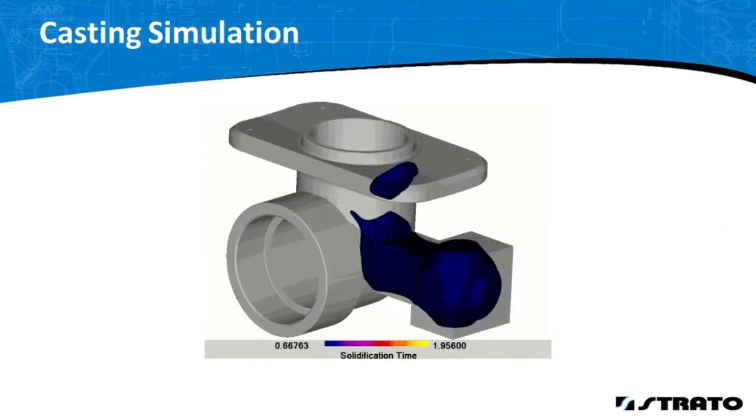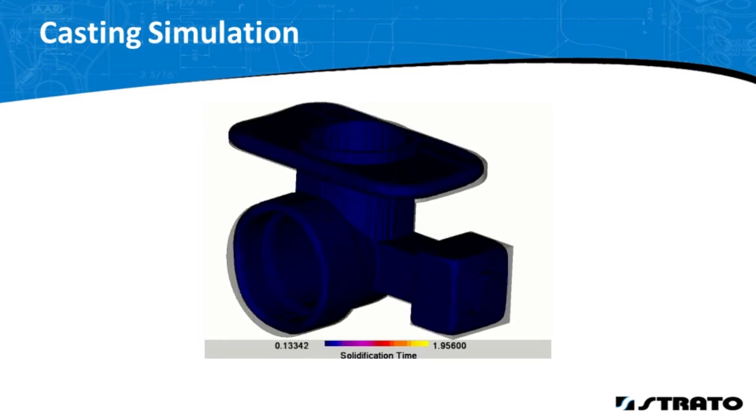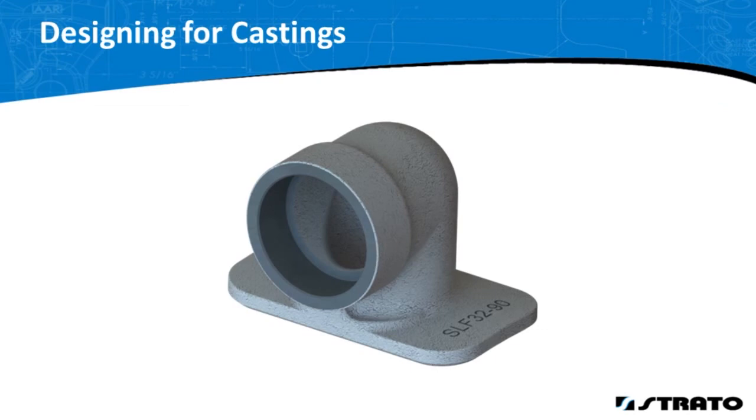Strato works closely with our vendors not only in the design of parts and tooling, but also in the process of casting a part. The steam fitting shown here has undergone a FlowCast simulation to identify why the vendor was having a high rate of failure. In this picture of the steam fitting, you see the results of the adjustments Strato engineers recommended after our analysis. Strato improved the design by adjusting the wall thickness and adding a reinforcing rib. The gating of the product was also adjusted. The result was the defect rate dropped from 30% to less than 1%.